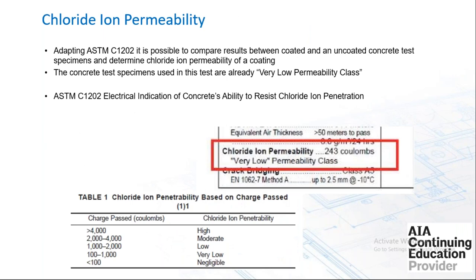Chloride ion permeability. This is a bit of a red herring in my mind and a waste of space, because the test is conducted on concrete, and within the confines of this test, ASTM C1202, concrete already has a very low chloride ion permeability. So when you see a test like this and a manufacturer claiming, oh, well, it has a low permeability class, it really means that the concrete was doing its job anyway without the coating.